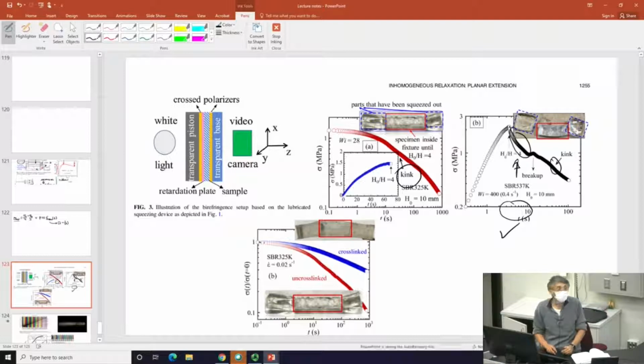If nothing happens, your sample should be smooth and homogeneous and bounce back. But it turns out it's bumpy, and we call it wrinkles. It's suggestive that even though it appears to be a single piece, inside something is happening in an inhomogeneous manner. And the only way to observe it is by lifting your piston, so that you will find the residual stress in different parts is different.